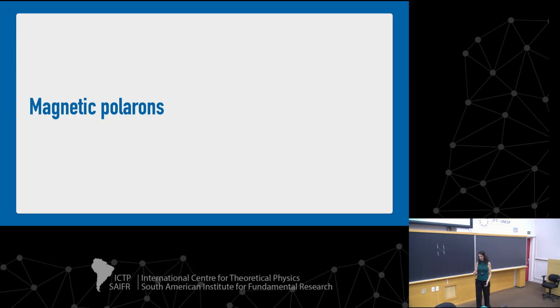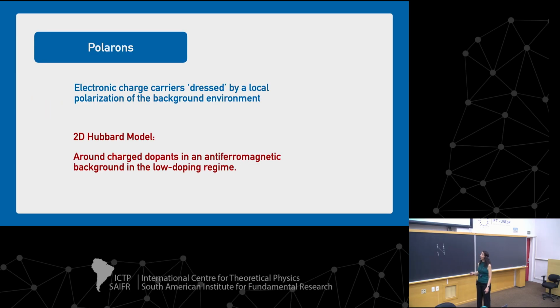And then the idea to study magnetic polarons. So for those who are not familiar, a polaron is what happens when you have a charge carrier. And here, once again, charge is not actually charged, but it happens anyway. And it's dressed by the environment. So you have a local polarization in the background because you put something in there. And the idea is to study that in the 2D Hubbard model. So you put a dopant, and you see how it bothers the antiferromagnetic regime that is there.